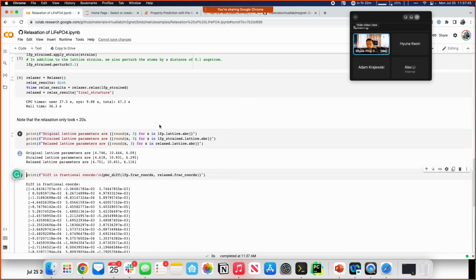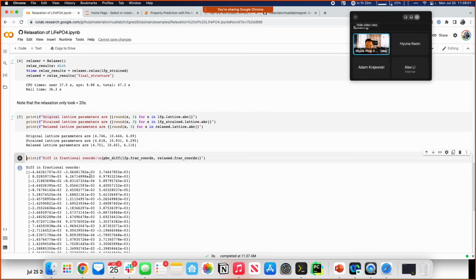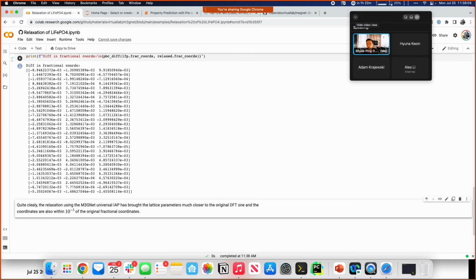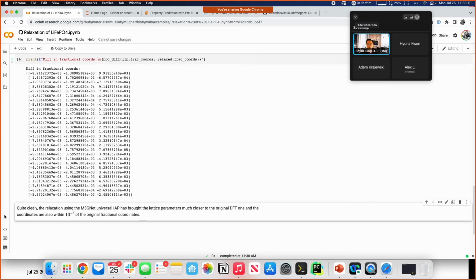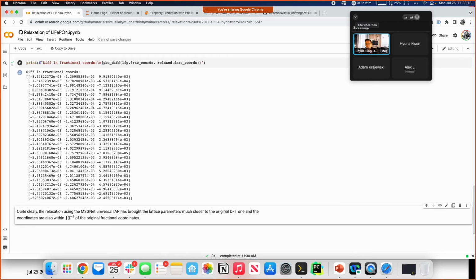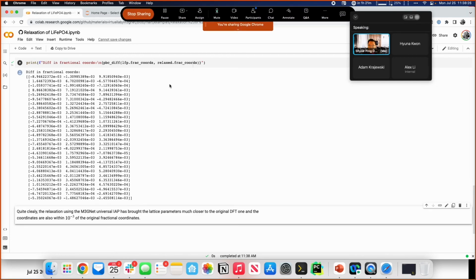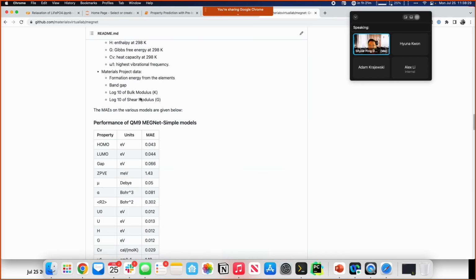Now, this is basically just showing you the results. So the original lattice parameters are this, and this is basically the strained lattice parameters. And what you will see is that the relaxation actually brings the lattice parameter much closer to what the original lattice parameters are supposed to be. And you should also be able to check the differences in fractional coordinates, and the fractional coordinates are definitely much closer, within 10 to the power minus 3 of the original fractional coordinates of LFP, okay? All right, I'm not going to show the cubic example, but rather I want to show the results of that relaxation,